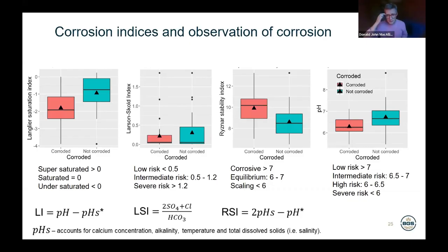But then when we looked at the pH 6.5 threshold, we did see that the majority of the sites where we had a pH less than 6.5, we observed corrosion, and where we didn't observe corrosion, in general, they were above that threshold. So it's some evidence for the effectiveness of that threshold as an indicator of corrosion. If we could move on to the next slide, please.